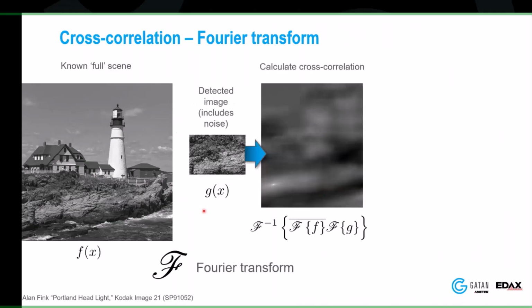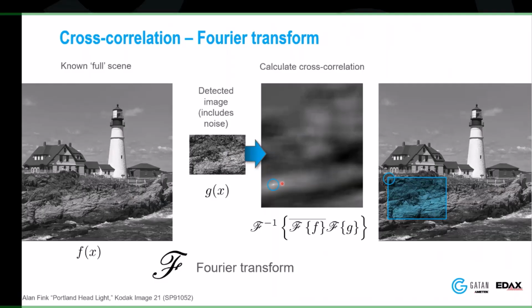Now, let's say instead of a dictionary method, I could do something a little bit different, and something a little more robust. What we can do with that is start doing these cross correlation techniques of image processing. This kind of holds true for dictionary as well, but this is the first step here. You can see here, this would be your pattern, and then it would run it through the algorithm to figure out where it best matched, and this hotspot would be what we found. So this is how it works in general, and this works for basically any sort of image correlations.